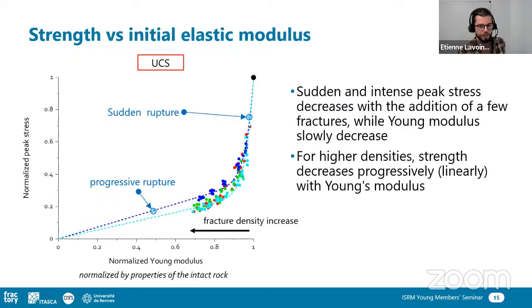If we now look at it in a different way, here we show still the normalized peak stress value as a function of the normalized Young modulus. If you have a smaller Young modulus, it means that you increase the fracture density. We can see that all the dots are quite well distributed on this kind of curve, and that you have a sudden and intense peak stress decrease with the addition of a few fractures, while the Young modulus slowly decreases. Meaning that as soon as you introduce a small defect, a small fracture, you will create a huge variation of peak strength in comparison to the intact sample. But we show also that for higher density, the strength decreases more progressively, almost linearly, and that's what we call the sudden rupture and the progressive rupture.